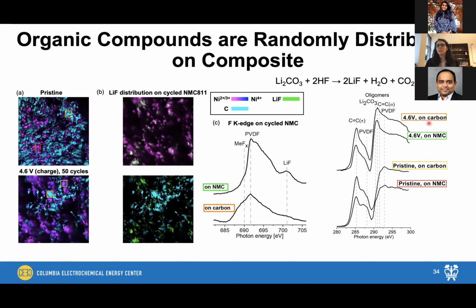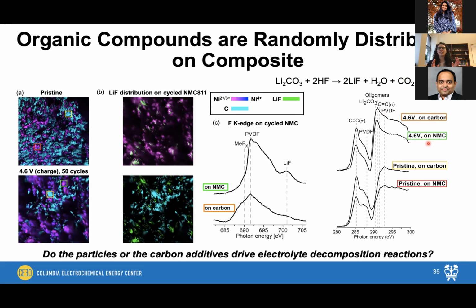And this is from the carbon particles. This is from the NMC811 particles. And what you can see is that they essentially look identical. So whatever we have on the carbon particles is the same thing that we have on our NMC811 particles. So we started to think this is either telling us that the particles and the carbon are driving the exact same chemical reactions, or something else is actually happening in this system that's causing the entire composite to be covered with the exact same carbon composition here.